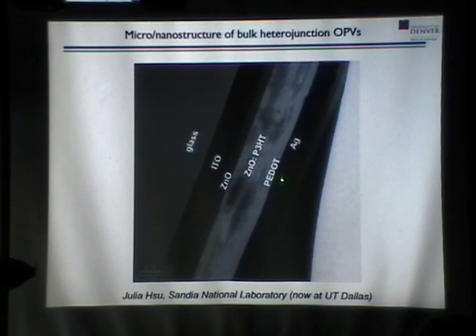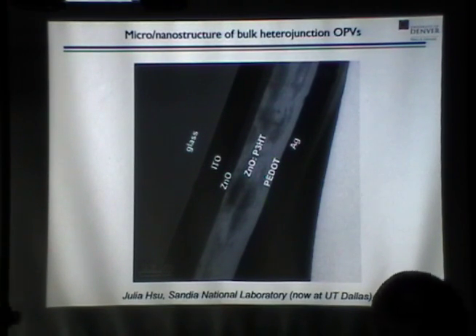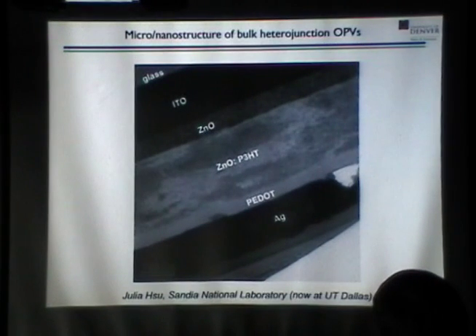And in this case, we have a mixture of P3HT, and we actually put in some zinc oxide nanoparticles, which have very good contrast in the TEM microscope, so you can see a little better the domains of the structure. And then here's some PEDOT on top and the silver. I think the next image is a little bit better.